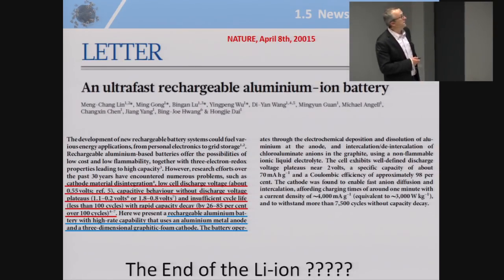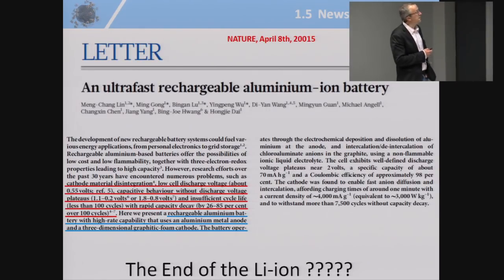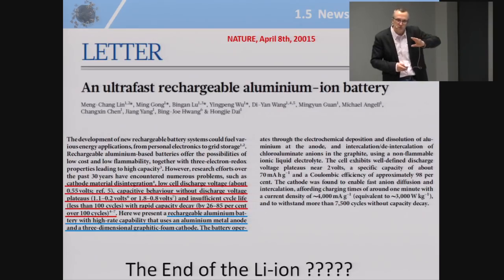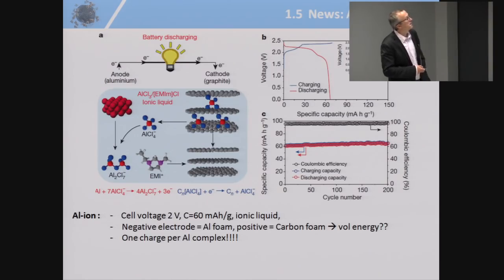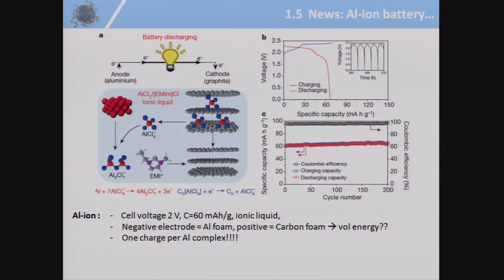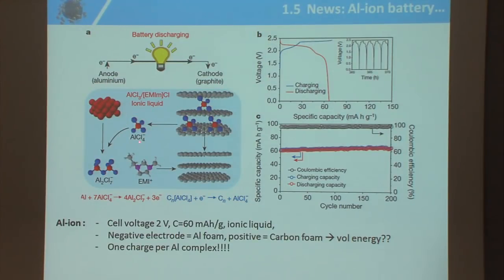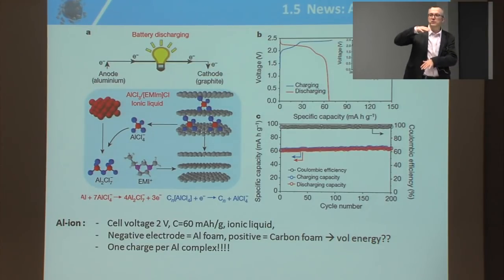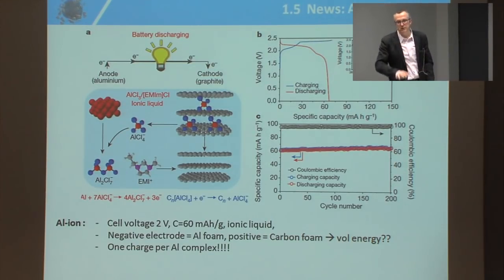So these guys from Stanford University said that they succeeded in preparing a battery based on the intercalation of aluminum ion. No one was able to make intercalation of aluminum ion, which is very tricky. However, if you have a look back at the details of the work, first they use complex aluminum ions. You see there is only 1 minus charge. There is only 1 charge per aluminum, not 3, only 1. So their interest is a bit decreased. And then they use an aluminum foil as negative electrode, and carbon foam as a positive electrode to put the materials. So a huge void volume, so volumetric energy density is very low.